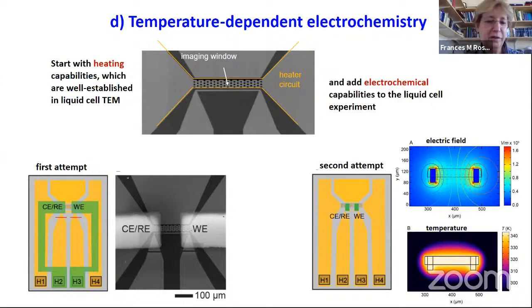And here's some examples of what you could do with heating capabilities. So the heating is done using a platinum heater that is aligned with the window and has little holes in it. Ordinarily you don't want to be looking through a heater made of platinum, because that's a lot of material to look through. So you have the heater circuit cut with tiny holes, or you have it maybe on one side of the window so it doesn't block the view very much. And then you add the electrodes on top, and there's a silicon nitride layer to keep everything insulated. So that's how you might include heating along with electrochemistry.